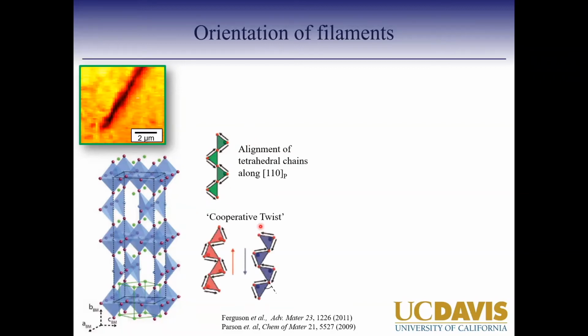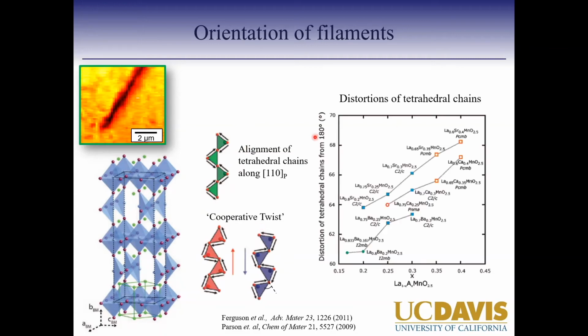So in manganites, for example, people have seen that this brownmillerite phase can actually go through a cooperative twist to reduce the dipole moment coming from these tetrahedrals. And that deviation can easily be from 60 all the way to 70 degrees for these tetrahedral chains. So that could be the reason why we are seeing these specific angles, but slightly deviated because of these cooperative twists happening in this brownmillerite phase.